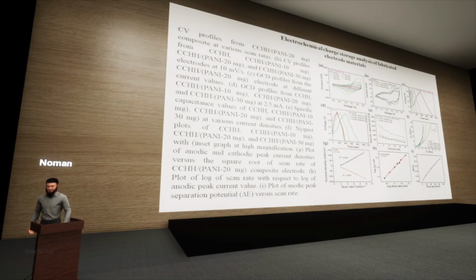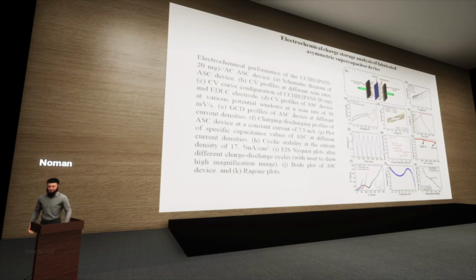So further investigation was carried out in which the charge density versus the scan rate, and capacity density versus the scan rate were plotted, and R square values were calculated. And similarly, the log of peak current density versus log of scan rate values were calculated so that we can be more sure that the electrochemical energy is thermodynamically feasible. So after making the electrodes and finding out the results, we have become sure that the maximum results were obtained for 20 milligram addition of polyaniline.